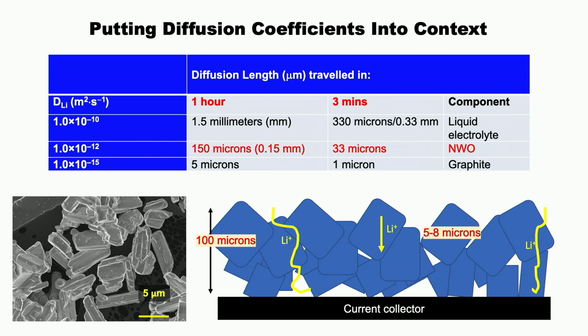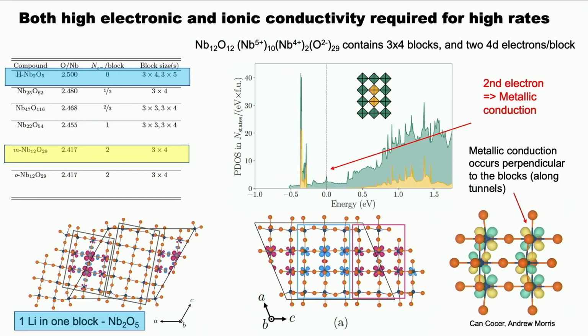And so you've got issues again of the plating that I was talking about. And so you need to nano size to get the rates. But if you're an NWO, you can move 33 microns, which means you can make these chunky monster particles that we made, and you don't have to nano size, reducing cost and reducing degradation. So that was fun. Not only do they move fast, you also get very good electronic conduction because you've got these edge-sharing octahedra that go down the material in the direction of the tunnel.